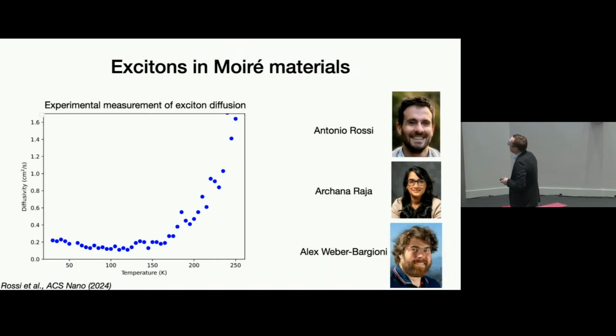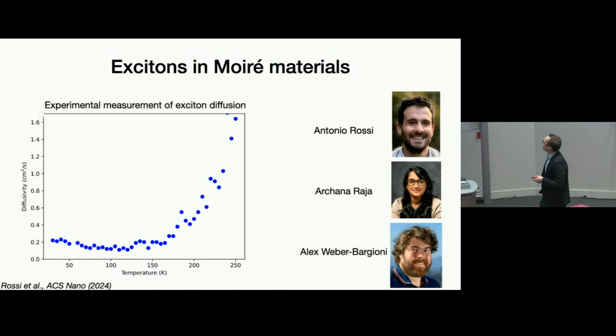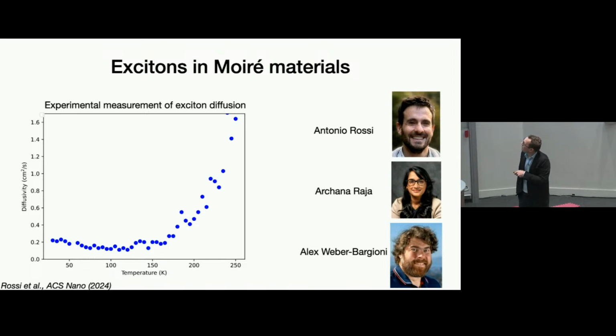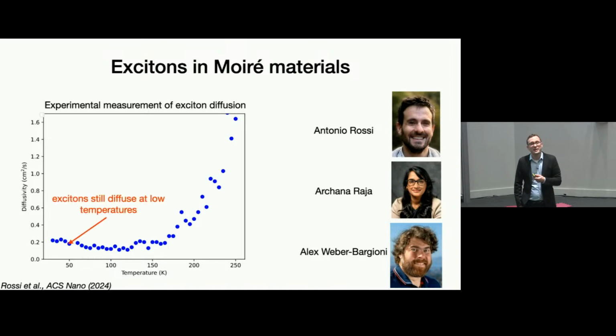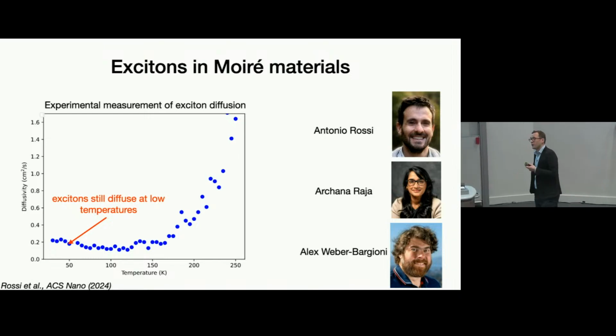So here, I'm showing you some experimental results from my collaborators at Lawrence Berkeley Lab. This is led by Antonio Rossi, who was working with Archana Raja and Alex Weber-Bargioni. And here you see the exciton diffusion, or the exciton hopping, as a function of temperature. You see at high temperatures, they hop a lot, and then it goes down quite a bit as you reduce the temperature. But what is interesting, it actually doesn't go to zero. It sort of evens out. In other words, the excitons still hop around at quite low temperatures. And that was very surprising. So this is something we wanted to understand.